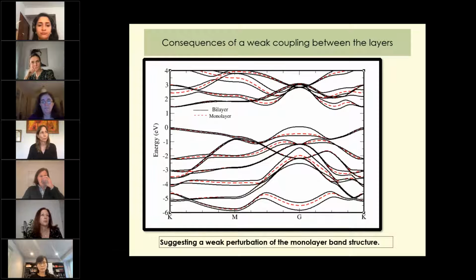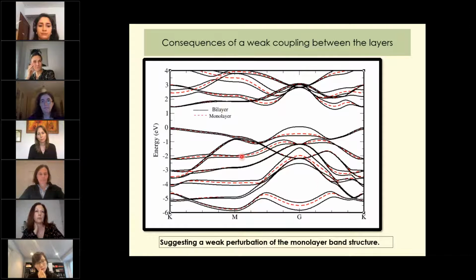And there should be a consequence of this very weak force on the electronic structure. And indeed, when you look at the electronic structure and plot it for a monolayer and a bilayer, which I'm showing you over here, what you see is that they're pretty much similar all over, which suggests that the electronic structure is very weakly perturbed when you have two layers. So why do we see these phenomena which you usually associate with correlated systems in these materials?